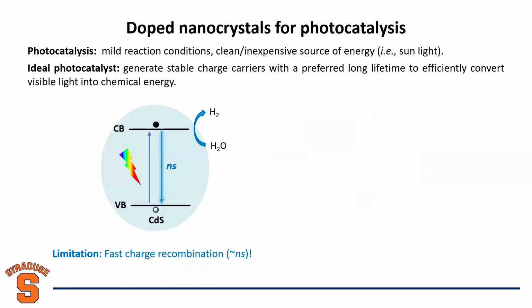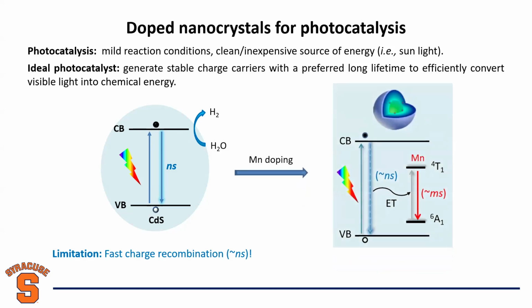But for ideal photocatalysts, we think we should generate more stable charge carriers that can be used for further chemical transformation, right? So in my group, how can we get that? What we did is, again, we introduced a manganese dopant there. Similar to the slide showing the solar concentrators, we have energy transfer to the dopant energy levels. Interestingly, and significantly, the lifetime of the excited state electron associated with the dopant is on the order of milliseconds.